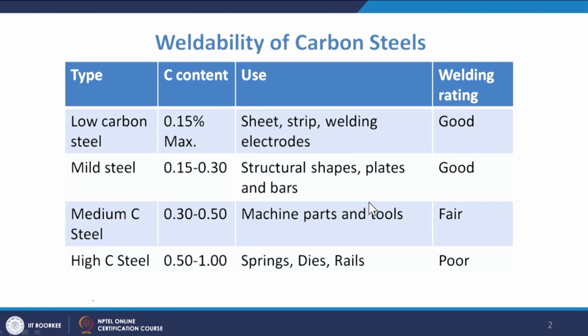And next is the mild steel, it is 0.15 to 0.3 percent, for structural shapes, plates, bars, the most widely used material. And medium carbon steel, that is 0.3 to 0.5 percent. It is mostly used for machine parts and tools. And high carbon steels, which generally have 0.5 to 1 percent carbon content, which we generally use for springs, dies, and rails. Coming to the weldability perspective, low carbon steel and mild steel generally have higher weldability because of their low carbon equivalent content. Medium carbon steel is moderate, and high carbon steel has poor weldability.